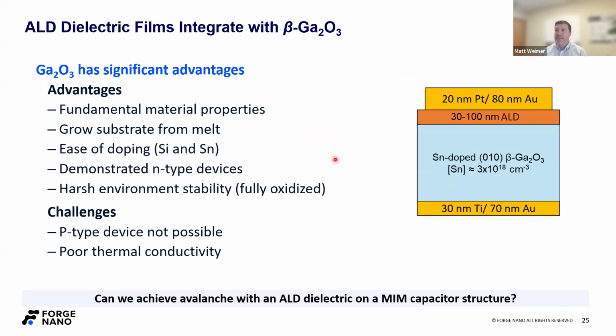Gallium oxide is also very interesting for other reasons. Personally, I think it's super interesting that you can grow substrates from a melt, just like you can with silicon. So from a substrate size perspective, there's a clear path, at least from that perspective, for scaling. It's also relatively easy to dope. These are the structures that we worked on. We worked with Ohio State on this, and this was the doping that they used. It's also fully oxidized gallium oxide. So if you think about putting it in a harsh environment where it's high temperature and some oxidizer around, it's not gonna oxidize further. That just doesn't happen.